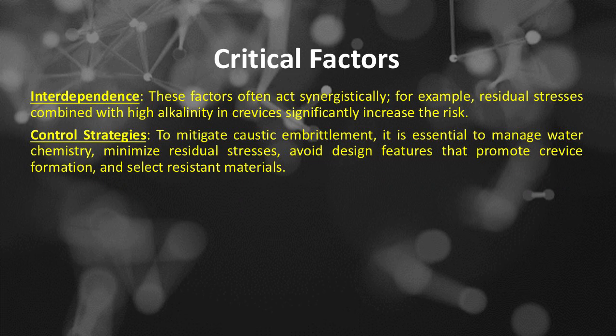Interdependence: these factors often act synergistically. For example, residual stresses combined with high alkalinity in crevices significantly increase the risk. Control strategies: to mitigate caustic embrittlement, it is essential to manage water chemistry, minimize residual stresses, avoid design features that promote crevice formation, and select resistant materials.